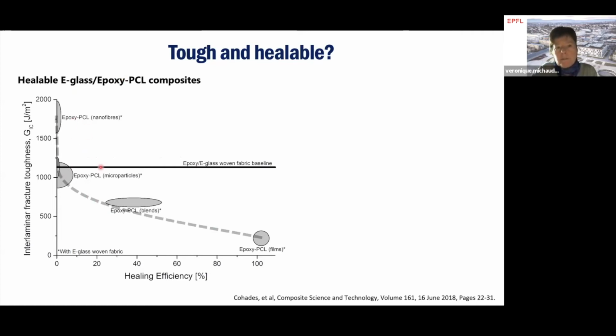We can get this, being the epoxy glass woven fabric baseline. With the PCL nanofibers, we get high toughness, but zero healing. This is the healing here. With epoxy PCL microparticles, we tried. We also got a good, decent toughness, but no healing. With the blends, we had a decent healing, but no toughness. And we also tried with films interleaved between the epoxy, full PCL films. We got, of course, very good healing, but we had no fracture toughness at all due to the presence of those PCL films.